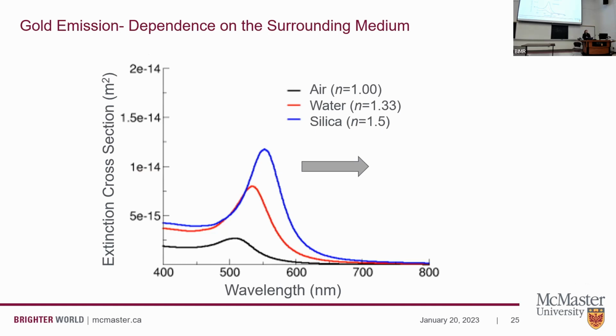So we wondered if there was any way that we could actually get this information. To do this, we looked at the signal of the gold tip itself, because gold also has an emission in this case. And the signal of the gold tip has a Lorentzian shape, as we can see here. And it depends on the surrounding medium. So here we have 3 examples where the blue one is in silica, the red one is in water, and the black one is in air, all 3 of which have a different refractive index. So this shows us that the gold emission will shift with the refractive index of the surrounding medium.